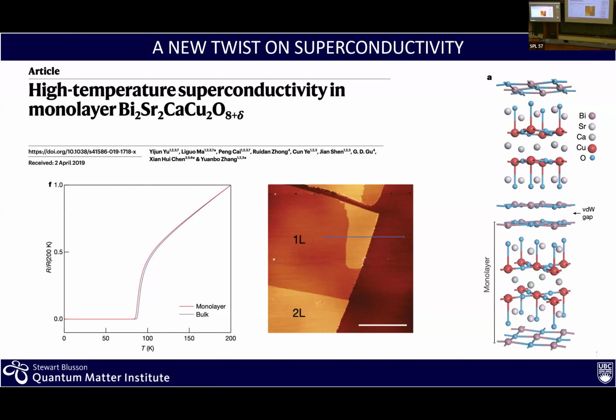And then in between here, they are separated with 2 blocks by what we call the van der Waals gap, or rock salt type layer. This is bismuth oxygen. So what you can do here, you can cleave the material very easily. So it really breaks at this very weak bond, to the point that you can make a single block like this. You can isolate a single block like that.